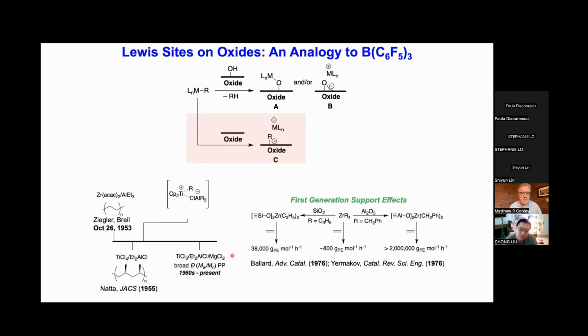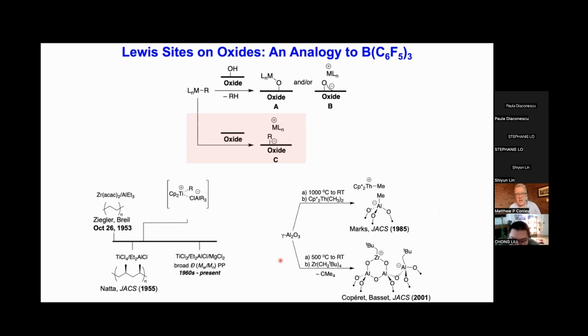Really the understanding of how these first generation Ziegler type catalysts that have evolved into more advanced mixtures of metallocene, oxides, and alkyl aluminums, how they evolve to form the active sites on an oxide. And so in some of the first generation insights into this, taking alkyl zirconiums reacting with silica or alumina, you get these wildly different polymerization rates. More modern techniques using solid state NMR show that one of the reasons for that is, if you take alumina and you dehydrate it at very high temperatures, you basically unmask Lewis acid sites that form these ion pairs.